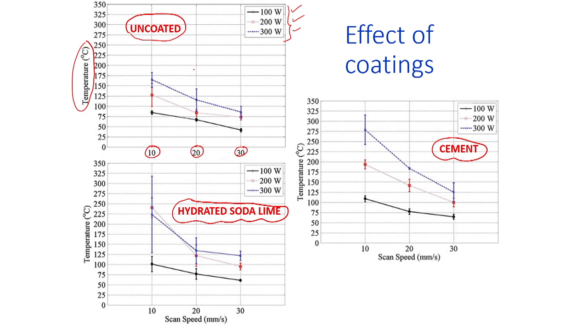You just notice for uncoated material, the maximum temperature was around 175 degrees Celsius for 300 watt of power, and this is achieved at 10 mm per second. So when the interaction time was less, the power was high, about 300 watt, the maximum temperature reached was about 175 degrees Celsius. Now for the same process condition, if we apply the hydrated soda lime, then you just notice that the temperature recorded was increased. So it went up to more than 225 degrees Celsius. For the same process condition, when cement was applied, then the temperature was further enhanced to 275 degrees Celsius.